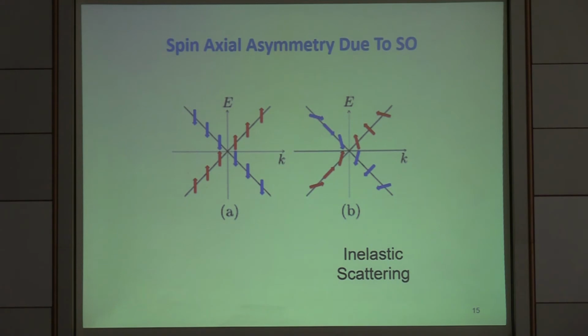And then, material-wise, this can also be related to spin axial asymmetry due to the spin-orbit interaction. Ideally, this spin momentum locking is strictly independent of k, but considering the spin-orbit interaction, the spin momentum locking is actually helical like this, axially dependent. So only when you have k equal to 0, spin up and spin down are opposite. Then at finite k, you can see these do not necessarily have completely opposite directions. Okay, so that causes an additional channel for inelastic scattering. For instance, if you have a finite temperature and a phonon is involved, then you can exchange momentum and cause this pair to flip together.